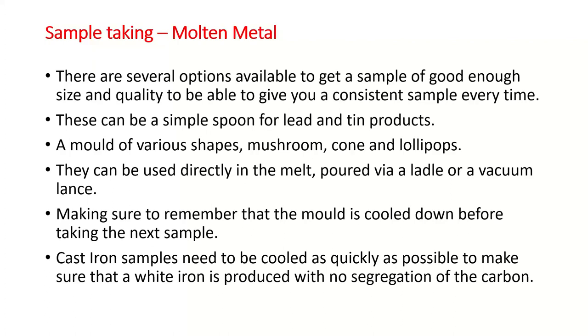Cast iron, I've already mentioned about the carbon going out into the grain boundaries. Keep working with cast iron, you need to make sure that you've got a white sample. The sample needs to be cooled very quickly to produce a white sample, and that makes sure that you've got no segregation of the carbon. The carbon actually stays within the crystal structure rather than coming out and going into the grain boundary. So it means that you're going to be able to measure carbon using this technique rather than it giving you a strange reading.